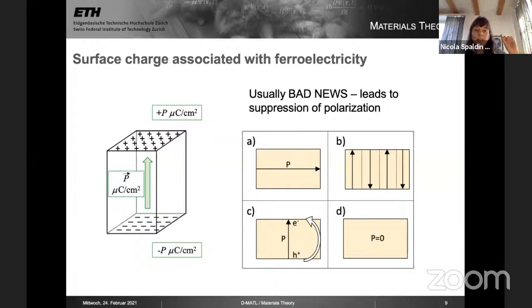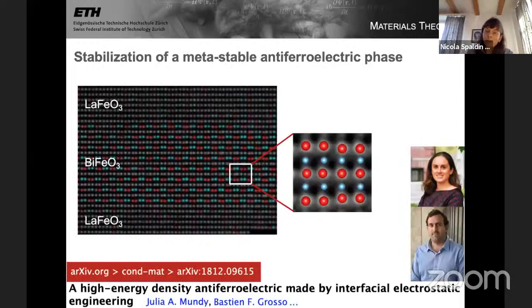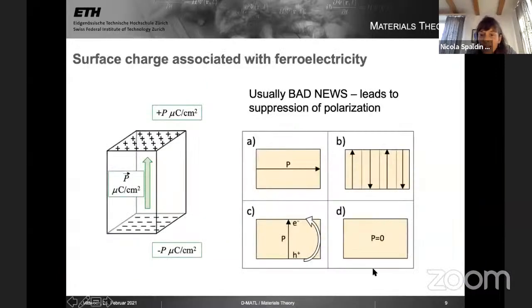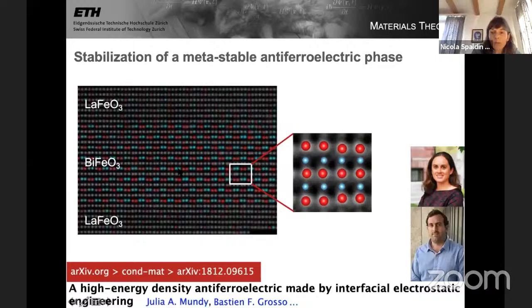So I want to show you where this surface charge in bismuth ferrite actually allowed us to do something positive, which was to, let me go back for just a second, to stabilize a rather interesting phase that has this property of having zero polarization. And it's a phase that's not the ground state if one doesn't have this special electrostatics, but it becomes the lowest energy phase as a result of the need to screen the surface charge. And so this is work done by Julia Mundy, who's now at Harvard, and Bastien Grosso, who's a student in my group, and our collaborators.